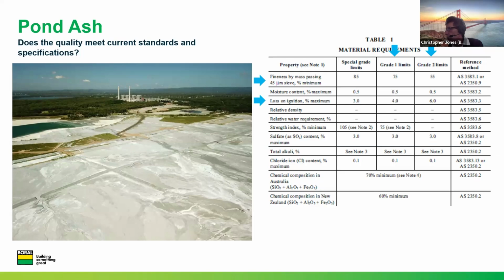Most concrete plants use grade 1 ash, but if for some reason we're unable to produce grade 1 ash from pond ash, we could supply the pond ash as a grade 2 ash, and it would still comply with AS 1379, which is the concrete standard. Grade 2 ash is likely to be less efficient, but it's certainly better than no ash.